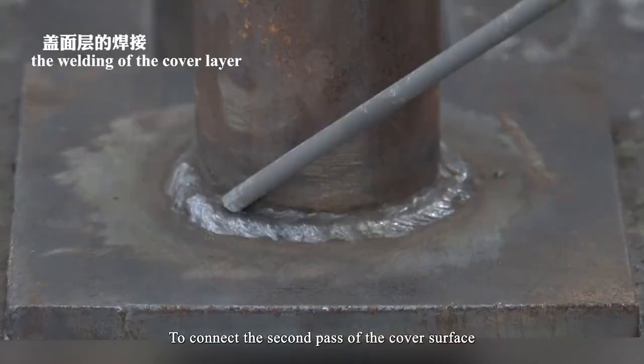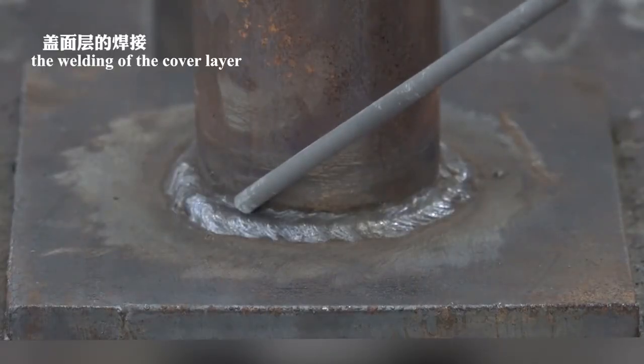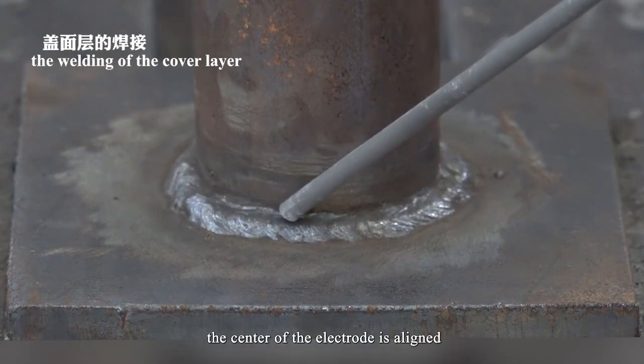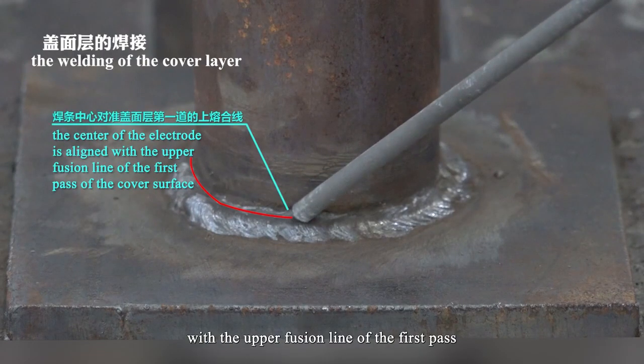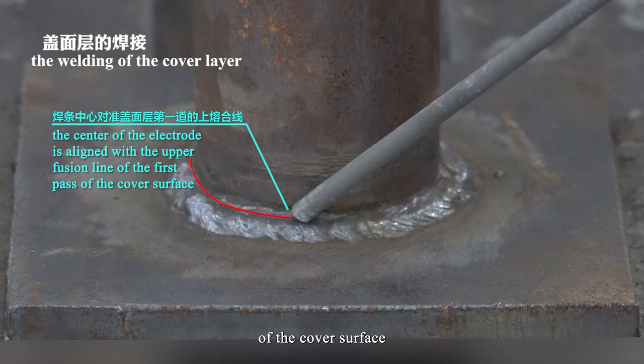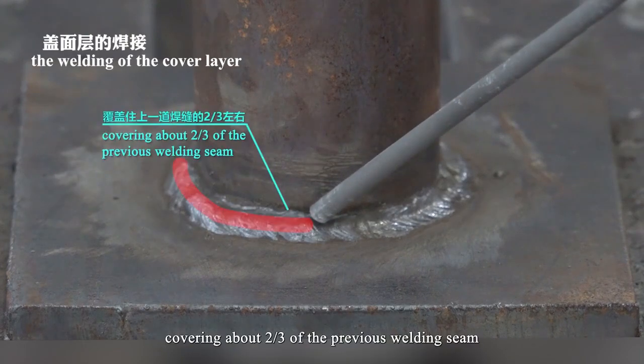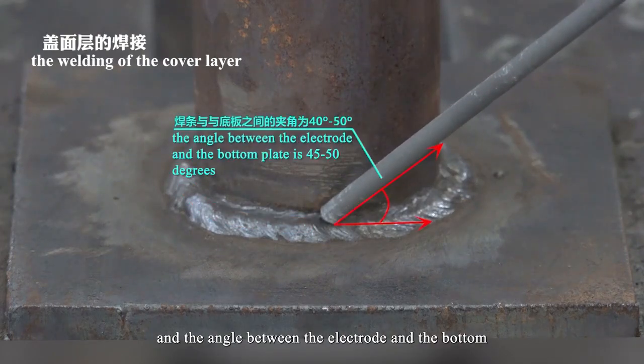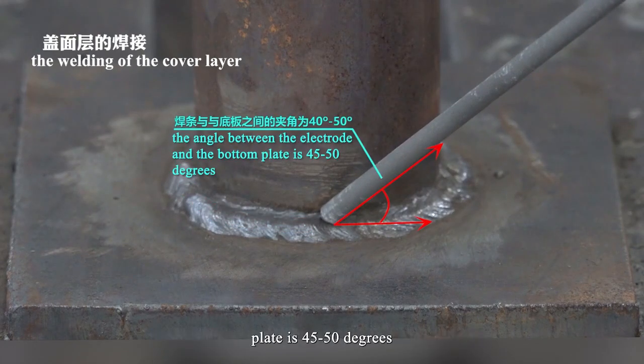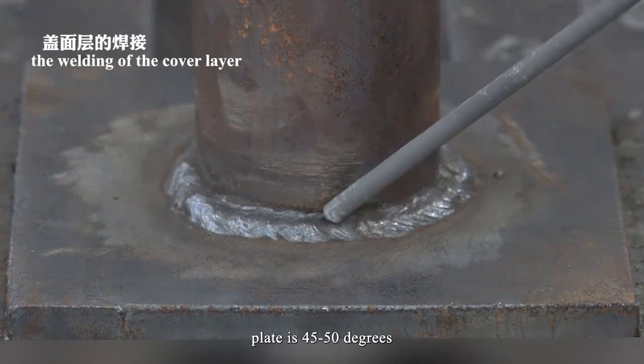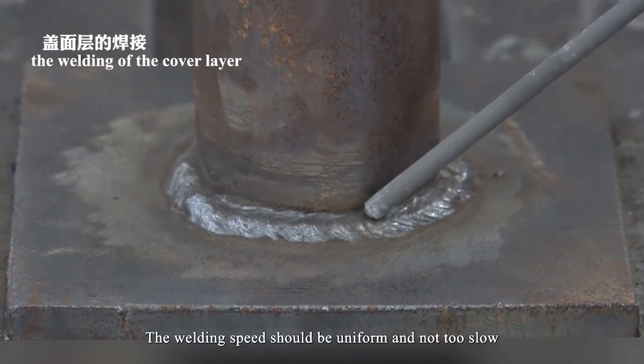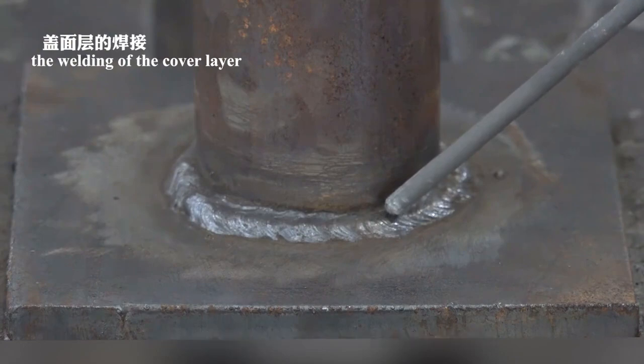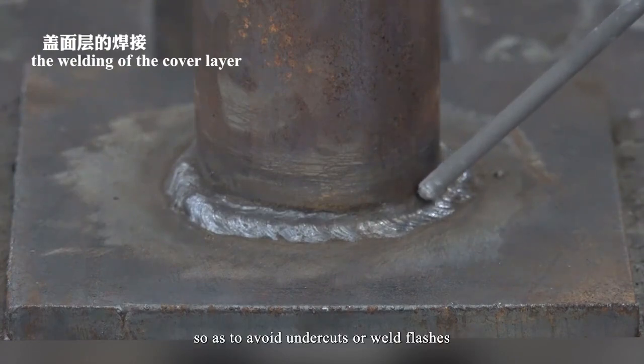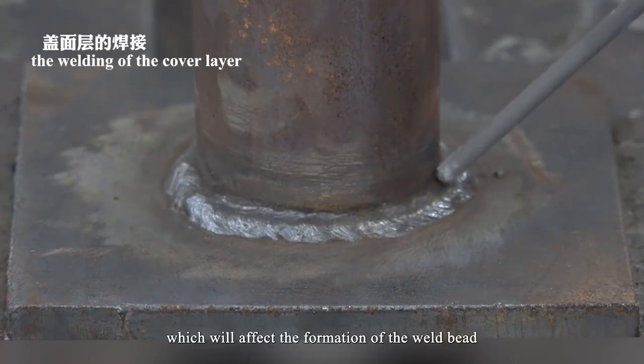To connect the second pass of the cover surface, the center of the electrode is aligned with the upper fusion line of the first pass of the cover surface, covering about 2/3 of the previous welding seam, and the angle between the electrode and the bottom plate is 45 to 50 degrees. The welding speed should be uniform and not too slow, so as to avoid undercuts or weld flashes, which will affect the formation of the weld bead.